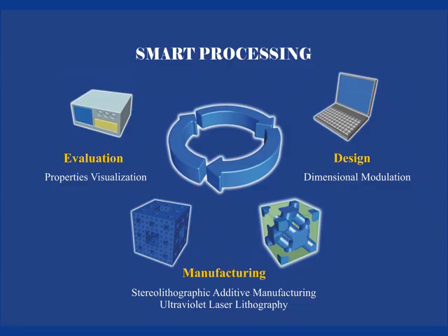In this investigation, we try to fabricate 3D structures by using an additive manufacturing process. At first, the 3D diamond structure was designed, and the 3D pattern was fabricated by stereolithographic additive manufacturing. The electromagnetic wave property was measured by a computer system and the result was fed back to the 3D design. By using investigation cycles like this, we can create ideal structures, with computer-aided design, manufacturing, and evaluation process.